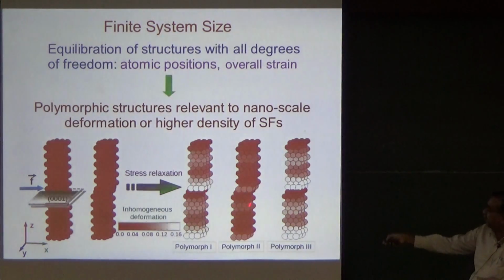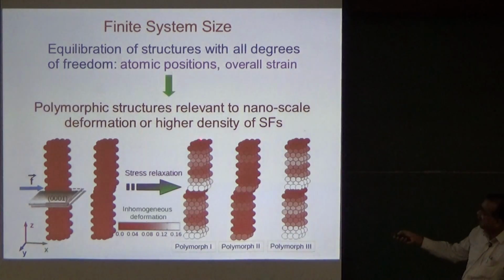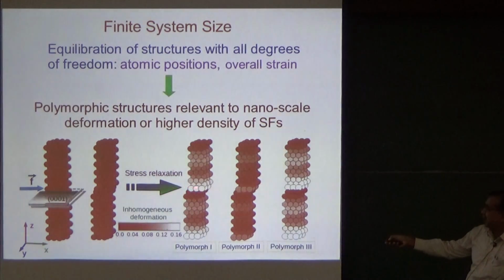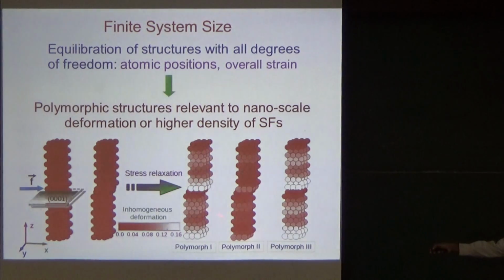We predicted 3 polymorphic forms of titanium here, and these are basically arising from stacking faults which are here and interacting with each other very strongly. The color code basically tells you the degree of strain in this lattice. So just like ferroelectric materials had inhomogeneous order in nanoscale, what we find is HCP metals can also have inhomogeneous strain fields in the nanoscale, and that gives rise to totally new structural form of these metals.